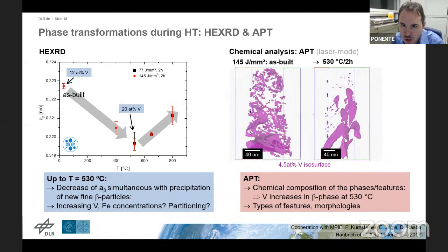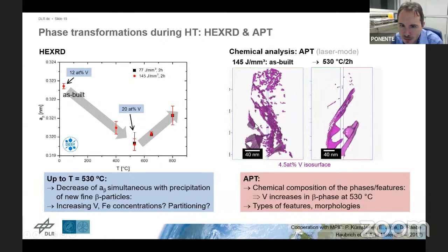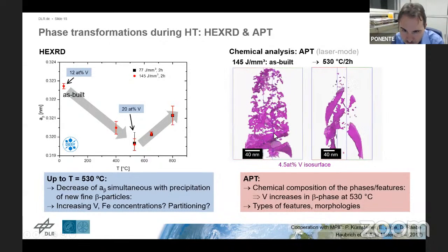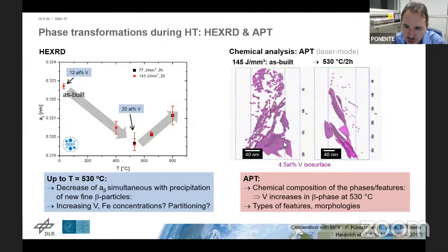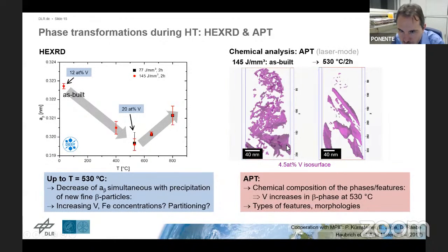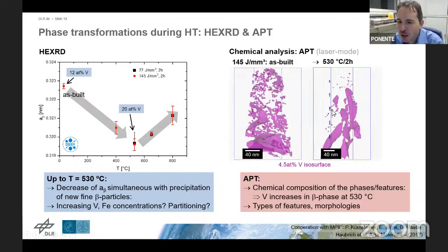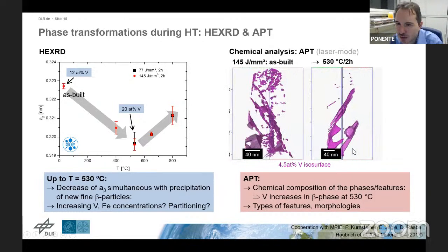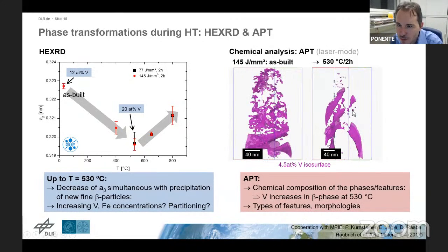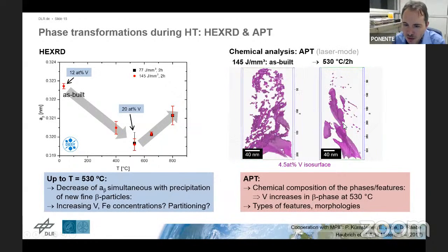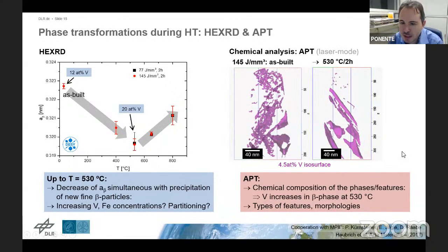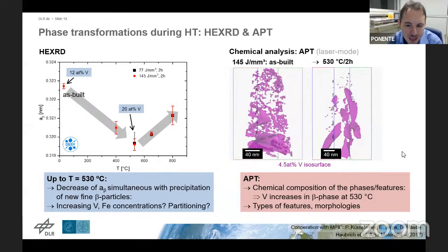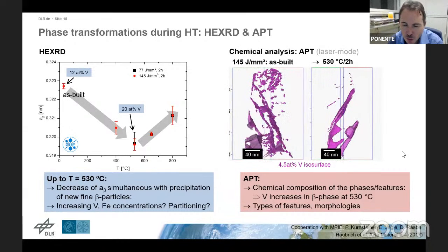And shown here on the left-hand side is the as-built state, where you can see at certain rotation angles film-like structures and a little bit plate-like structures at the bottom that I will show later on again. Whereas here on the right-hand side, at 530, this film-like structure is mostly broken up and it looks more like particles. So the APT is going to give us a lot of insights in terms of the morphology of the beta phase, but also the chemical composition.